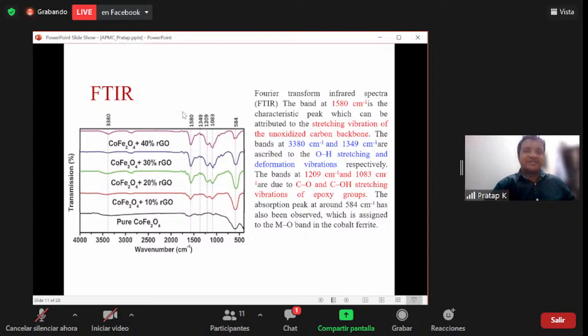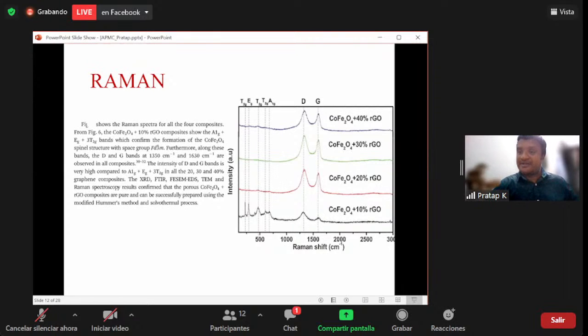There is a peak at 1580, which is a characteristic peak of the stretching vibration of the unoxidized carbon backbone. There are bands at 3380 and 1349, which can be related to OH stretching and deformation vibrations. There are also bands at 1209 and 1083, which are C-O and C-OH stretching groups. The absorption peak is also observed at 584, which belongs to the cobalt ferrite M-O bond. So using all these techniques, we have confirmed that cobalt ferrite is exactly formed.